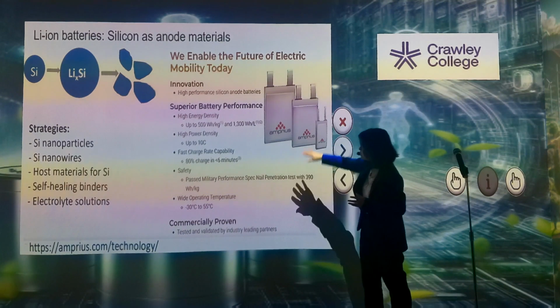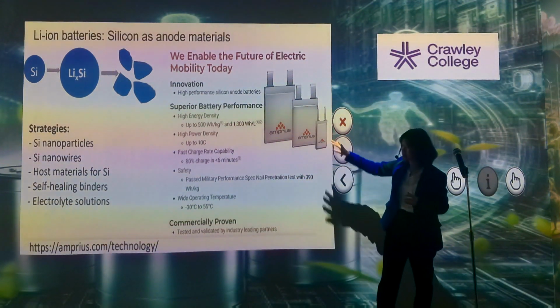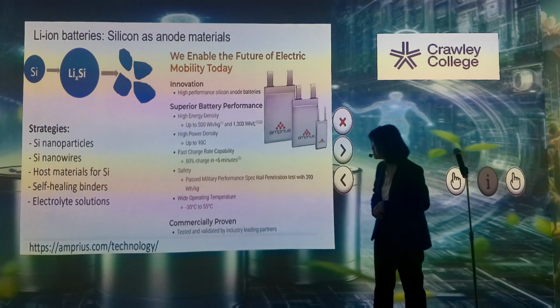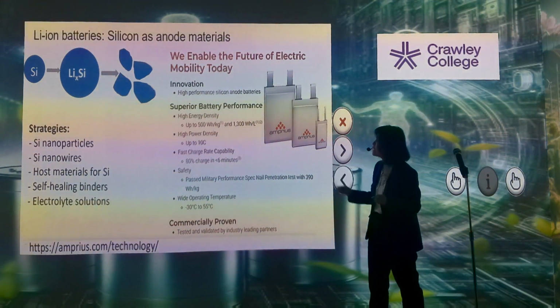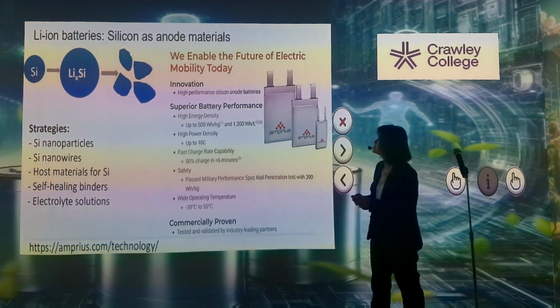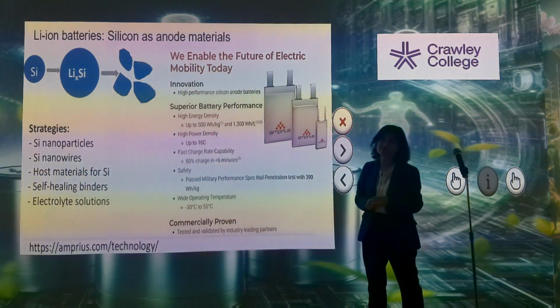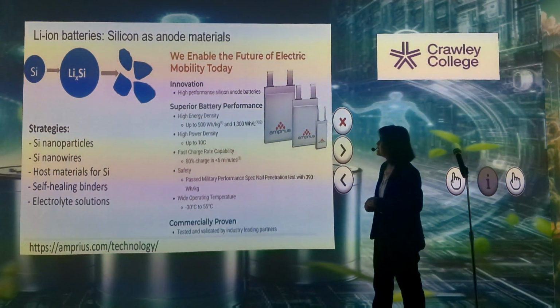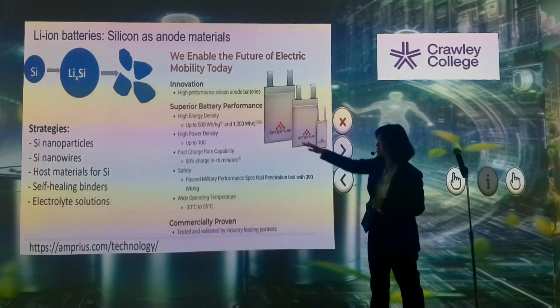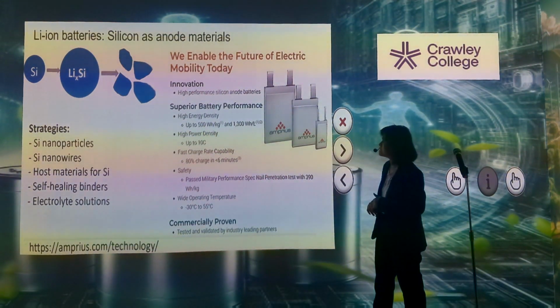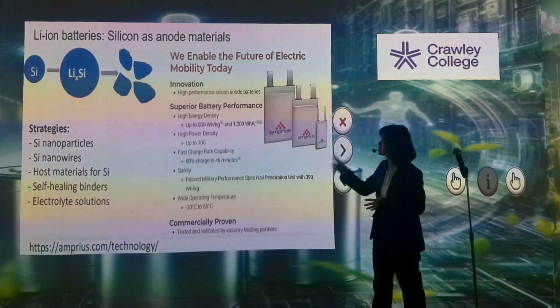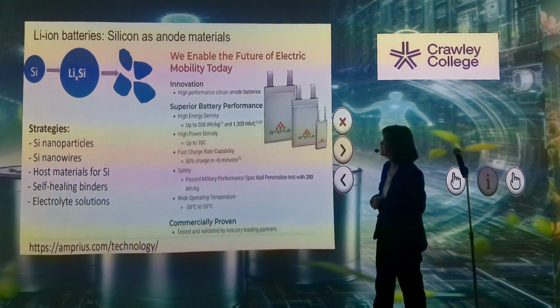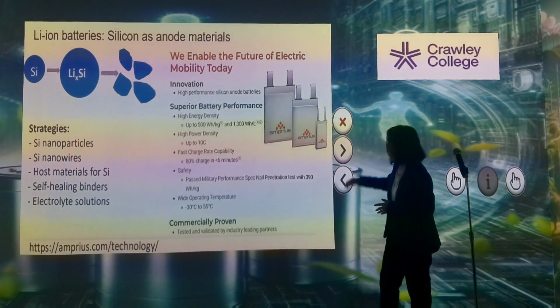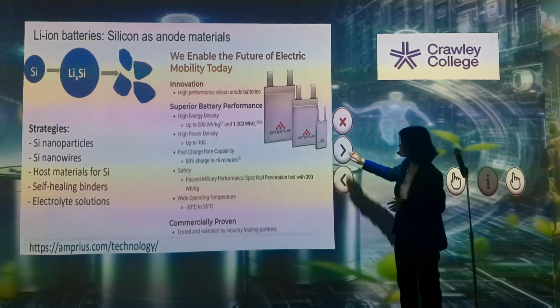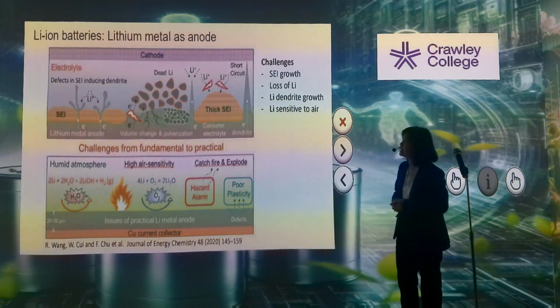And I show you here, this is a US company, a spin-out technology from Stanford University, where they have successfully managed to integrate a silicon anode in the lithium-ion battery, and they achieved very high energy density, 500 watt-hour per kilogram, and very high power density, and can charge at a very high C rate, charge very quickly, and have good safety. So there are products available on the market now.